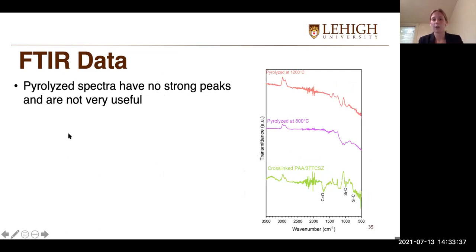And here I also did some FTIR with my pyrolyzed samples, but as you can see, the pyrolyzed spectra have no strong peaks and they're not very useful because there's no hydrogen in them, and there's really not much there.